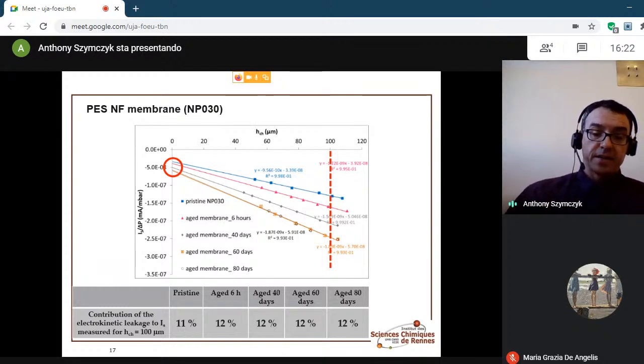In this case, the electrokinetic leakage represents around 11% of the total signal that is available from experiments. The intensity of the leakage varies with aging, but the contribution of the electrokinetic leakage phenomenon to the experimental signal does not vary when the time of exposure to chlorine increases.